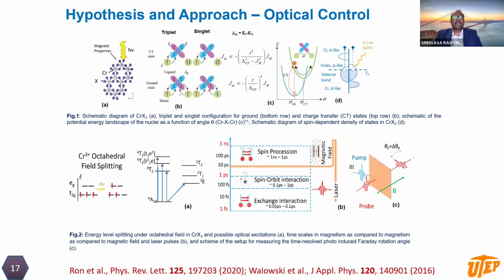So going further, here is a hypothesis for photo excitation of these crystals. We take a crystal, and the crystal has a ground state and an excited state or charge transition state, and we have a bunch of exchange interactions. So we tune the minima of the potential well, basically by choosing the transitions here, whichever are prominently strong upon photo excitation, and track the response by applying pulses at different time scales.